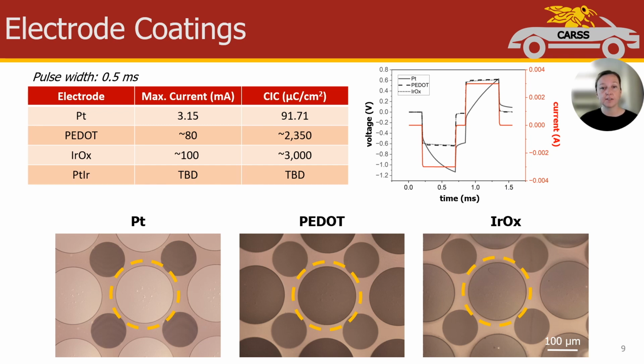In other terms, this test looks at the polarization of the electrode system in response to charge injection. When using bare platinum electrodes, the CIC is roughly 90 microcoulombs per centimeter squared, allowing a maximum current amplitude of just over 3 milliamps with a 500 microsecond pulse width. We also investigated electrode coatings to increase the CIC and allowable current injection.